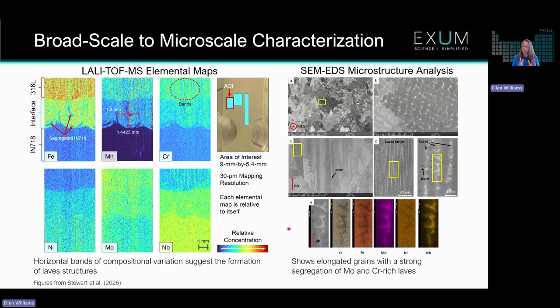Again, looking on a much smaller scale with the SEM on that microstructure and grain scale, and able to point out that, yes, in fact, there do seem to be these laves strips, and interpreting them as a segregation of molybdenum and chromium. So this is, again, just an excellent representation of how mass boxes, broad scale elemental maps with micron resolution complement the microstructure and grain scale understanding that something like a SEM-EDS gives you.